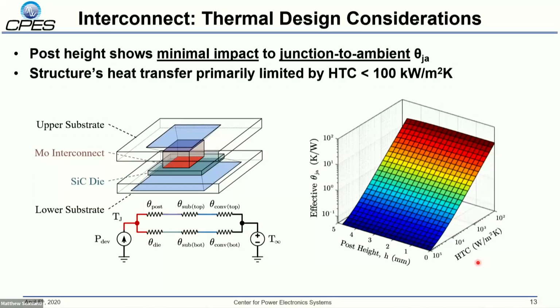It doesn't really become a function of the post height until we get into excess of 100,000 watts per meter squared Kelvin. So this is partially what motivates the decision to go direct jet impingement, so we can get these higher heat transfer coefficients and get down to a range where we actually see that sensitivity.